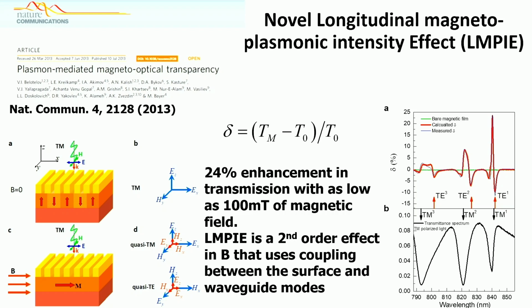Here, with an applied magnetic field, there's a waveguide mode and the plasmon-mediated local field. Because of the coupling of this plasmon mode and the waveguide mode, we can see enhanced transmission. With as low as 100 millitesla, we can enhance the transmission by about 24%. So this has been demonstrated.